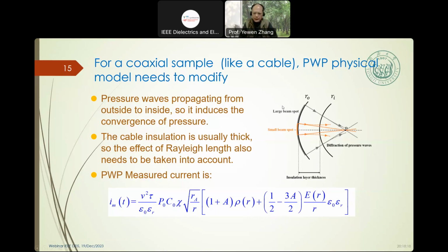So the laser spot cannot be too small. For the planar sample, this is not a problem because a planar sample is usually 1 millimeter or 2 millimeters, not very thick, so the laser spot is usually very big. For the measurement current, like this one, even without any space charge, E is not 0. E is also a function of the radius. So the current is also related to the field, the convergent field.